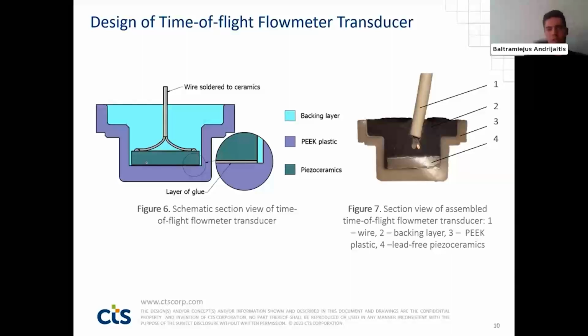However, there are some challenges in designing and assembling the flow meter. First of all, choosing the correct material and thickness for the matching layer. I'm talking about the casing material here. Also, we must choose robust glue and achieve as thin a layer of glue as possible while assembling. Also, to ensure parallelism of the casing material's outer and inner surfaces with respect to the ceramics flatness. And here on the right, you can see the section view of the assembled lead-free time-of-flight flowmeter, which we used in our assembly, and it is also involved in our results.